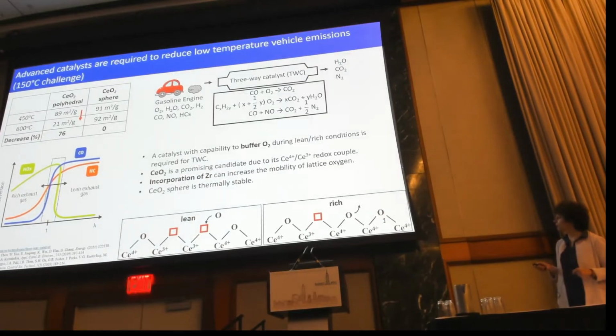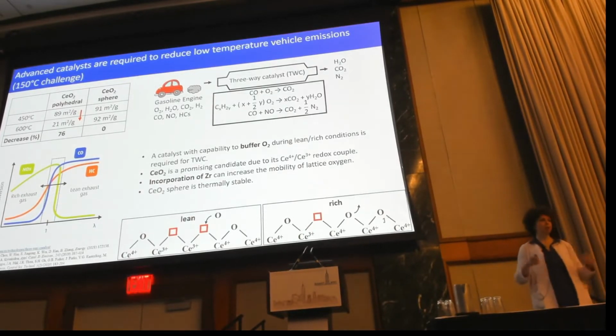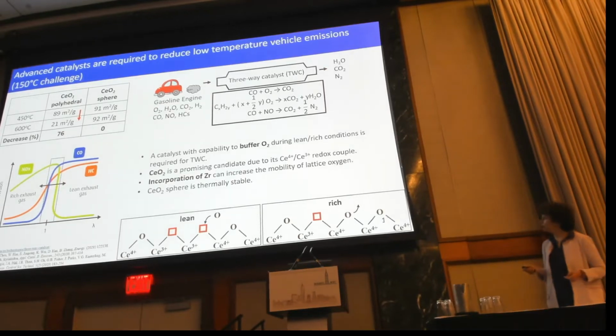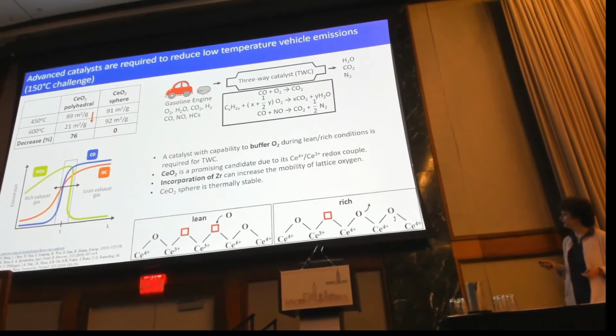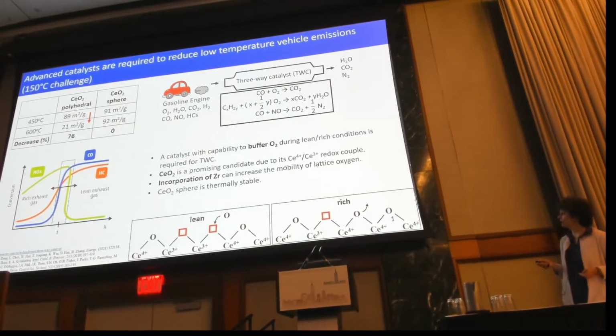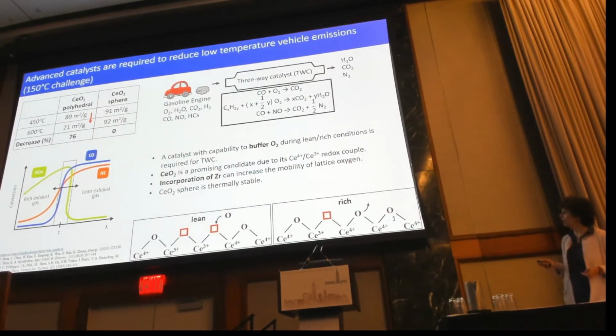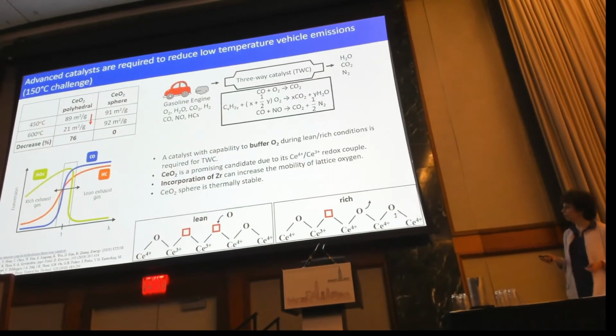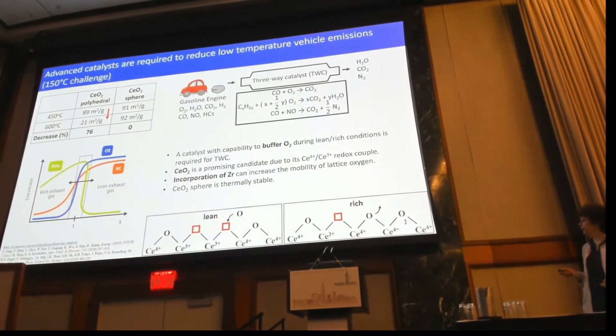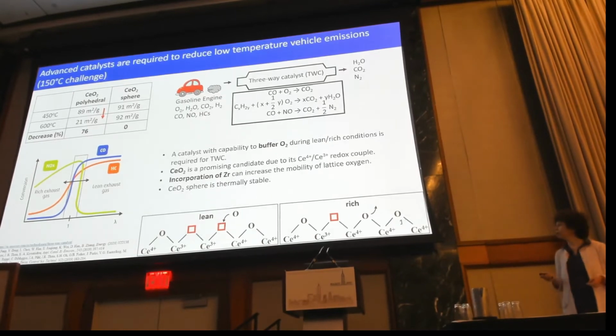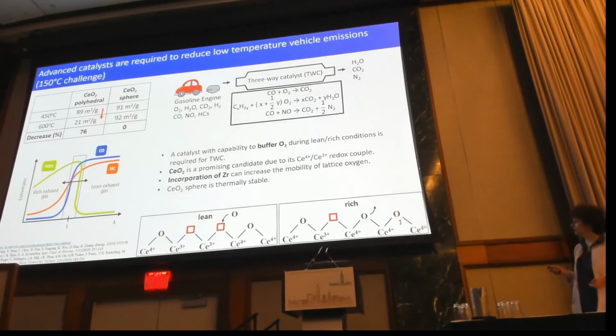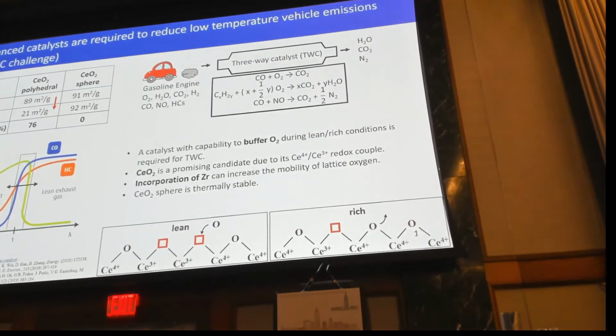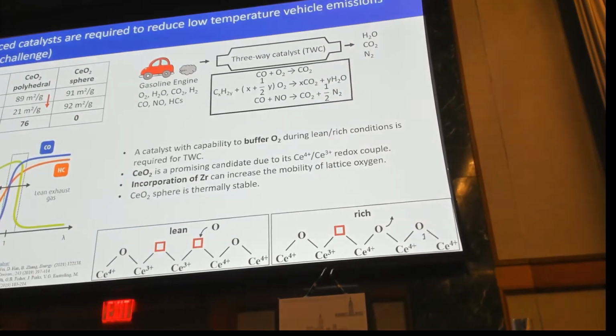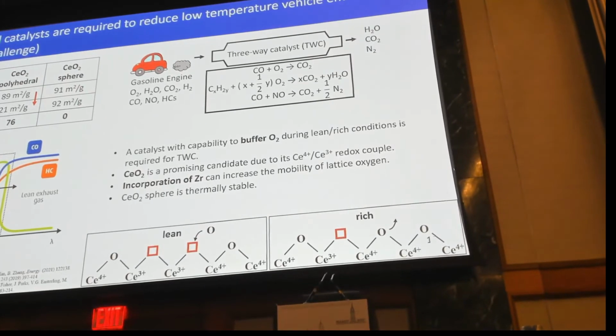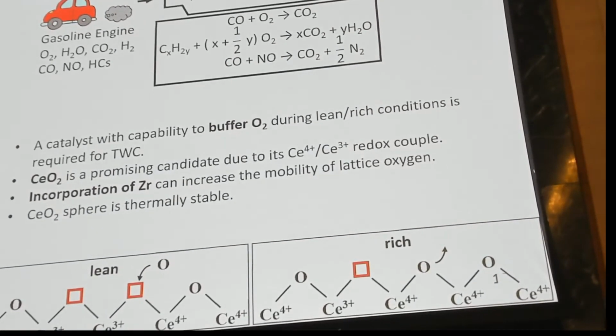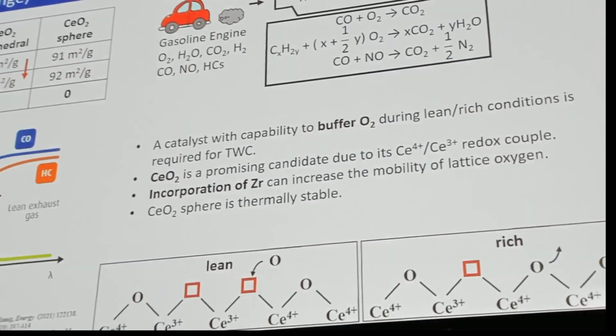So we synthesized some polyhedral ceria. Polyhedral ceria is the most commonly used ceria. And we noticed that the surface area of this ceria really decreases from 89 meters squared per gram to 21 meters squared per gram when we change the calcination temperature from 450 to 600 degrees C. And so, of course, this is not desirable. So we synthesized some ceria spheres. I'll show later how the materials are synthesized. And we noticed that these materials are more thermally stable, and we can see that the surface area is maintained when it's exposed to the same conditions as the polyhedral ceria.